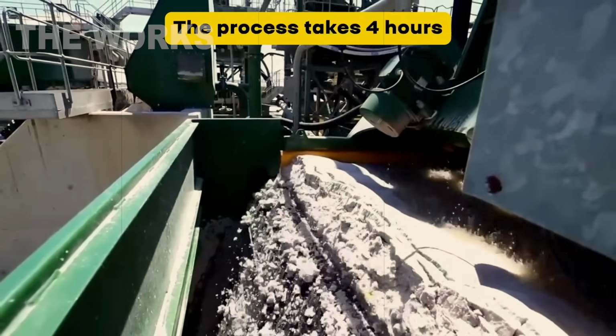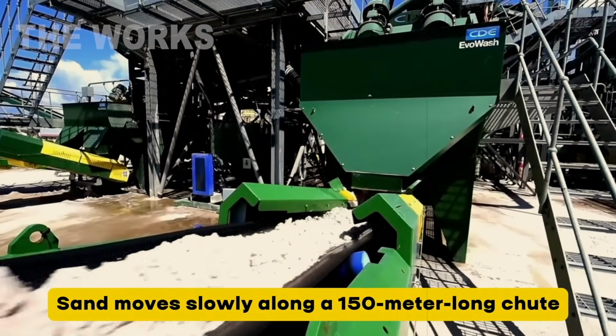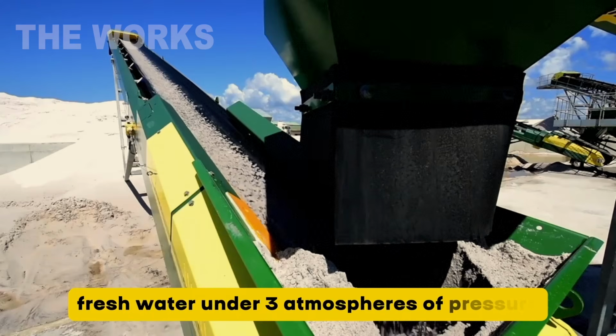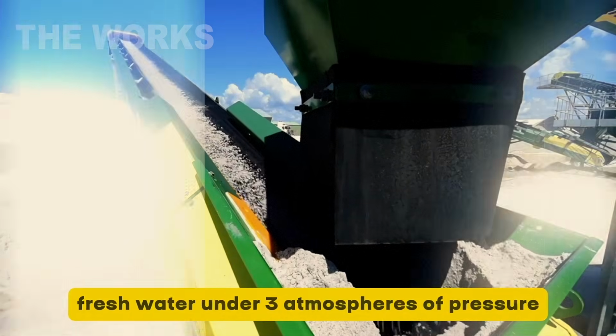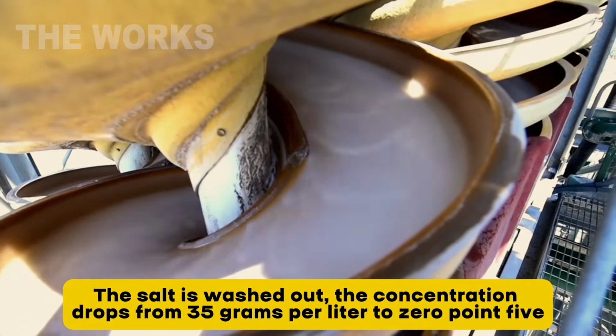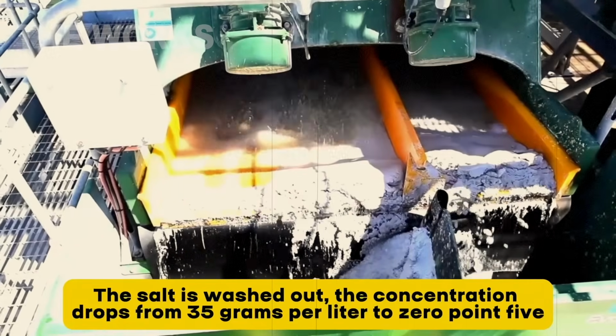The sand slowly moves through a trough about 500 feet long, while pressurized freshwater, at 3 atmospheres, pours down from above. The salt washes out, concentration drops from 35 grams per liter to 0.5.